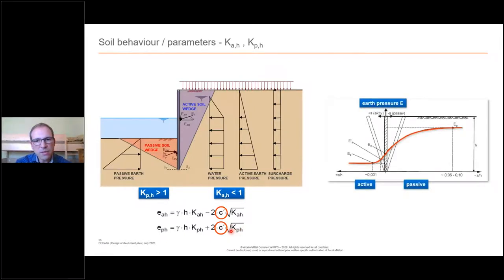Now, you know also that in order to achieve this full active or full passive pressure, you need a deformation of the soil. So on the active side, it's only like 0.1% of the height, but on the passive side, you need much more. So here in the sketch, you see that's 5% approximately of the height.